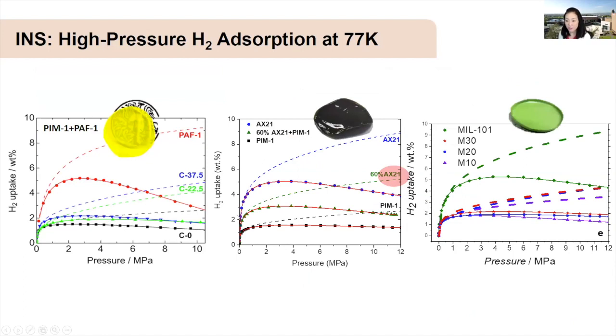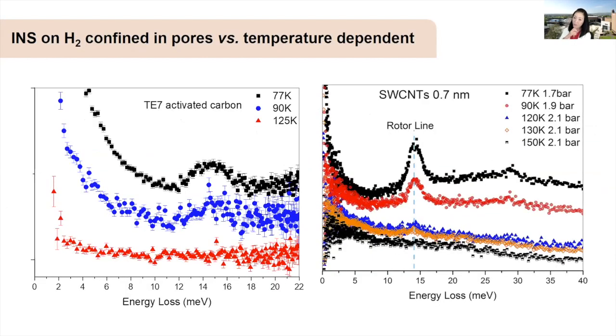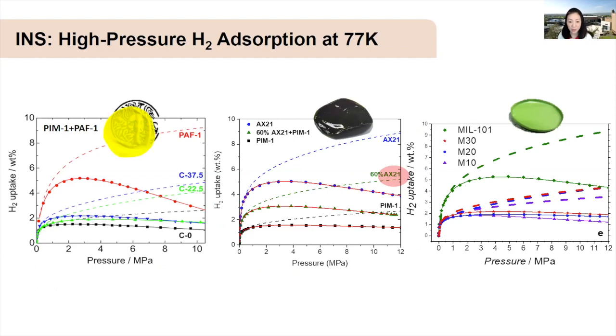And then the key information here is how much hydrogen the membrane can store. So the maximum hydrogen capacity is about 6 weight percent at 120 bar. So you can see the trend. If we continue to increase the pressure, the uptake will continue to increase, but 6 weight percent is already beyond the DOE target, the target set by the Department of Energy. So this is a practical application developed based on the theoretical study by neutron scattering.